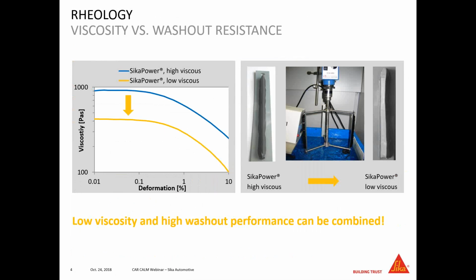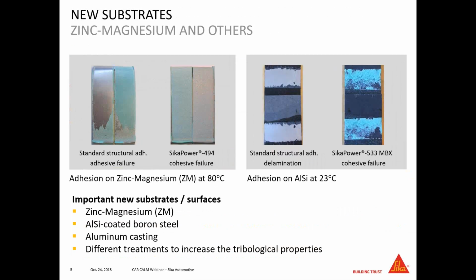It's not so difficult to reduce the viscosity, but the main challenge is not to lose wash-off performance. Today's adhesives can actually do both. They can be very low viscous and at the same time show excellent wash-off resistance. You can see this on the picture on the right side, where you have two beads of adhesive. One is a high viscous material and one is a lower viscous material. They get spun in a water bath, and obviously these beads should not be deformed or even washed off. As you can see, these pictures are after the test, so they're very stable. They show very good performance in that aspect. So one aspect of today's and also future adhesives will certainly be low viscosity.